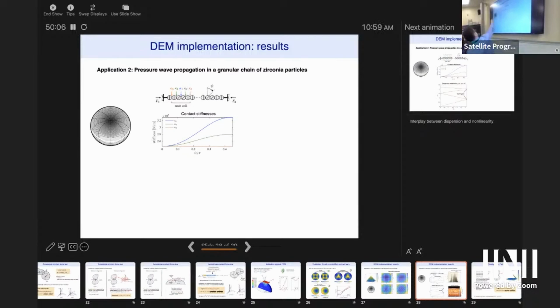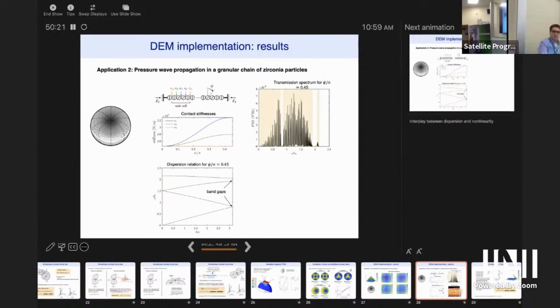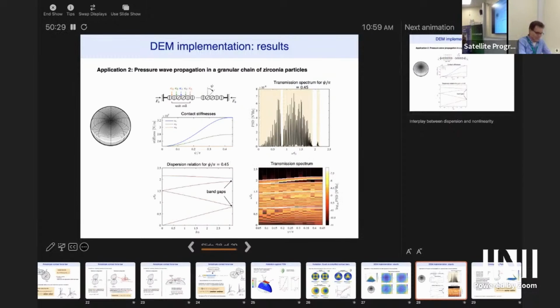So for example, if you just have a string of these anisotropic particles and you control the angle of tilt, let's say it goes vertical, vertical, tilted, tilted, vertical, vertical, tilted, tilted, if you control that angle of tilt, you can actually tune the band gap sequence. So you can decide what frequencies to filter out without having to change the particles. It's a cool little application of this. You can make a shock absorber to absorb frequencies on the fly.